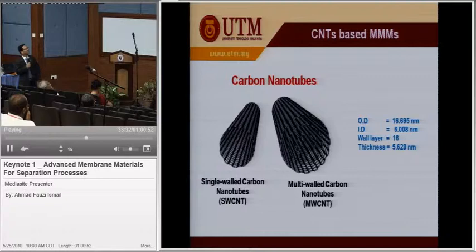Carbon nanotube, you can see the outside diameter, 17 nanometer. The inside diameter, 6 nanometer. And we produce multi-wall, which is about 16 layers. And the thickness is 5.6 nanometer. Remember, everyone can produce this. If I am from petroleum engineering, I can produce this. From mechanical engineering, should be double the capacity.